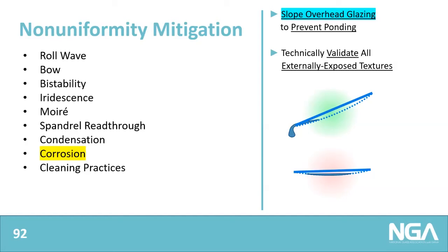And then as that water evaporates, the contaminants within the water would increase in concentration. In other words, if the level of contaminants stays the same, the amount of water reduces. And so as the evaporation process completes, there's a large level of concentration of contaminants, and that could corrode the glass. So if we have overhead glazing corroding, that's not an issue with the glass itself. That should be addressed in terms of the sloping of the glazing to prevent ponding in the first place.